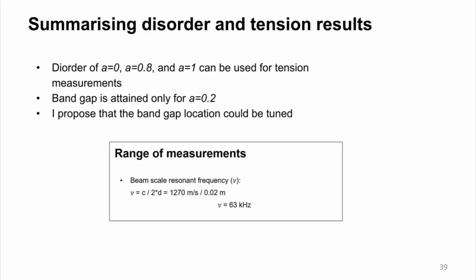Summarizing the results for disorder and tension, some of the disorders of 0.0, 0.8, and 1 could be used for tension measurements, sensing the tension, because they do depend on tension, and the sensitivity is very non-monotonic, so the peak features change vastly across different tensions, and that could be a potential application of these. Band gap is attained only for some of the disorders, specifically for disorder of 0.2, and the band gap is robust under change of tension.